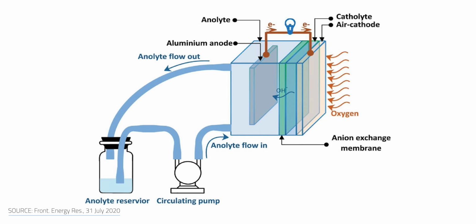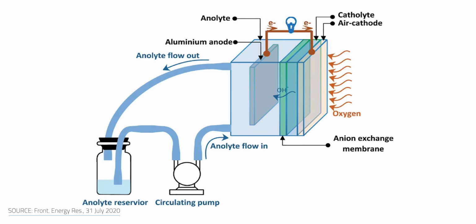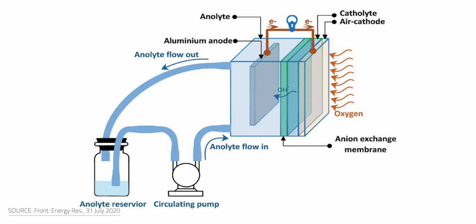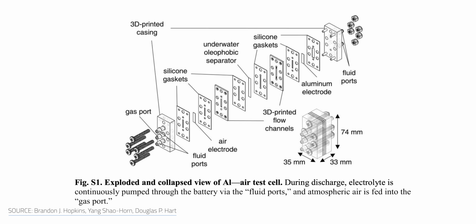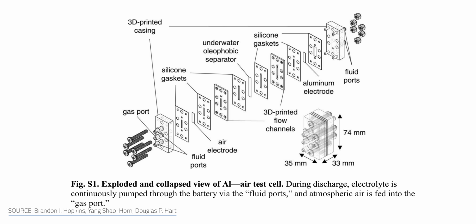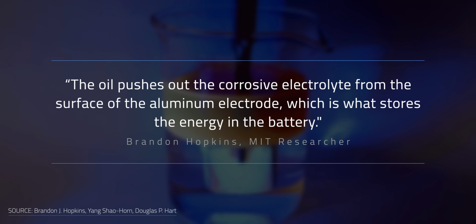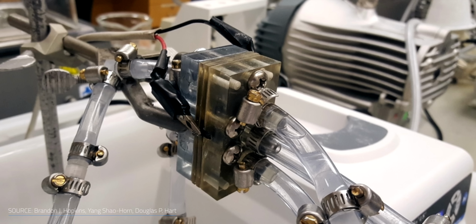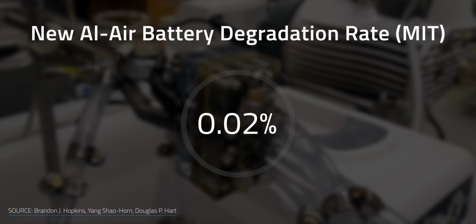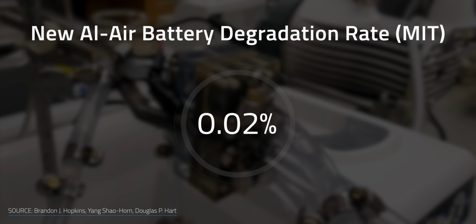To get around the corroding electrolyte issue, it's been suggested to use a pump to pump the electrolyte out of the battery while it isn't being used and then pumping it back in when it's needed. It's a bit of a brute force solution, but aluminum corrosion can still cause problems by clogging the pumping system. To get around this, researchers from MIT have designed a system that utilizes oil pumping. Brandon Hopkins and his research associates noted, "The oil pushes out the corrosive electrolyte from the surface of the aluminum electrode, which is what stores the energy in the battery." This approach resulted in energy loss of just 0.02% after a month of running the battery.